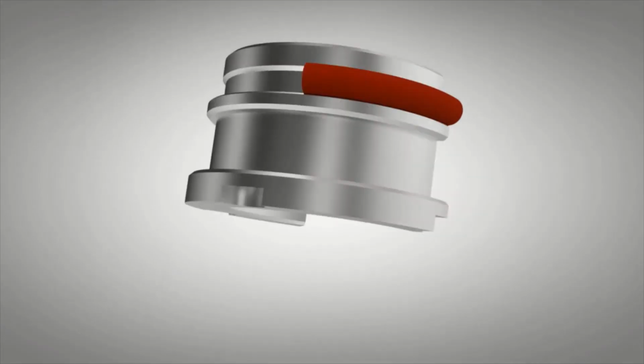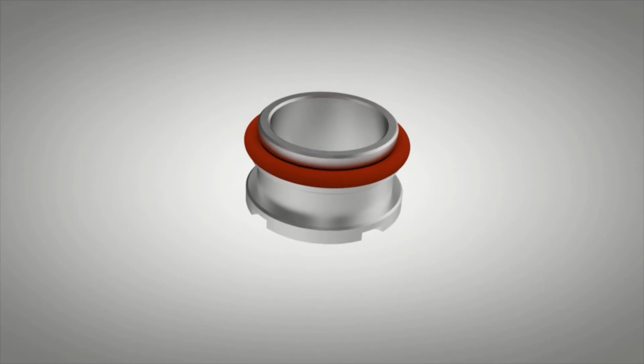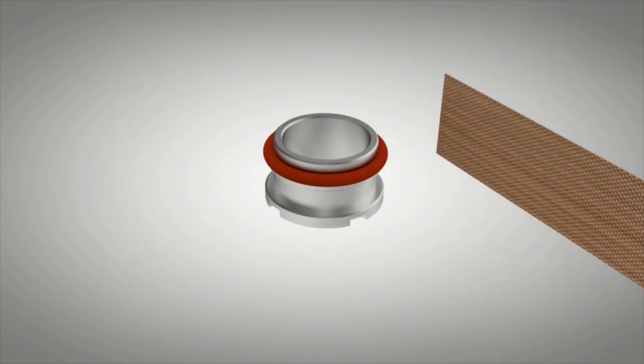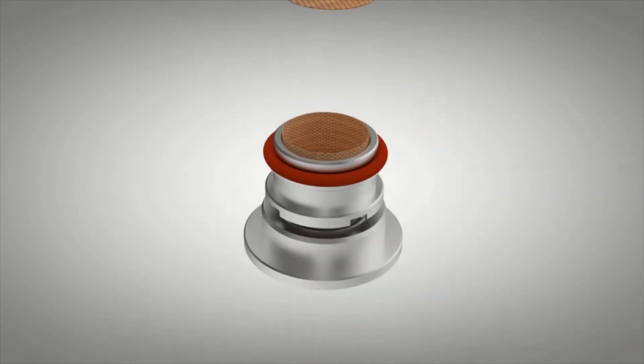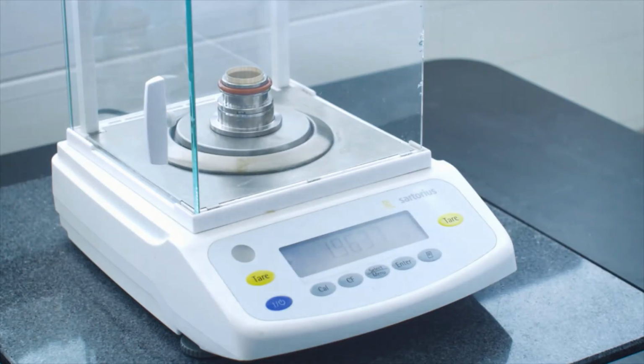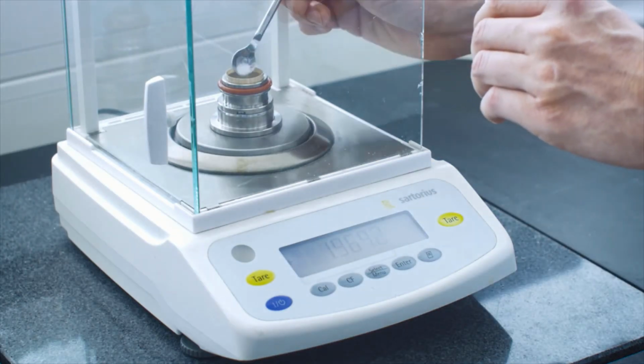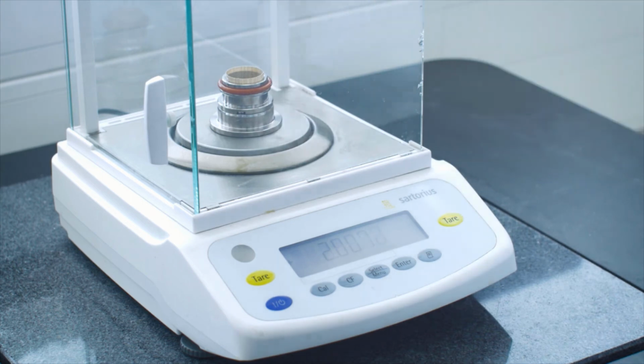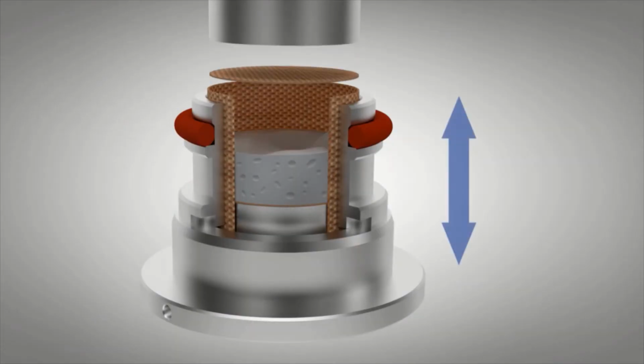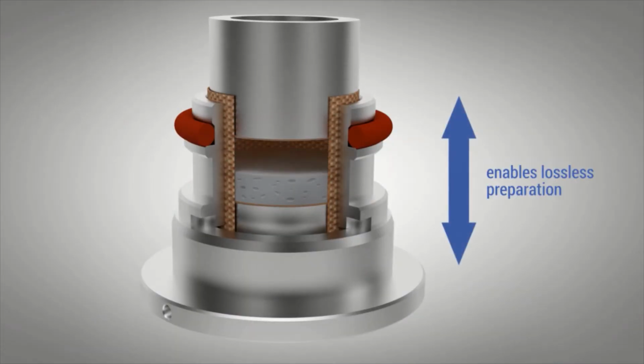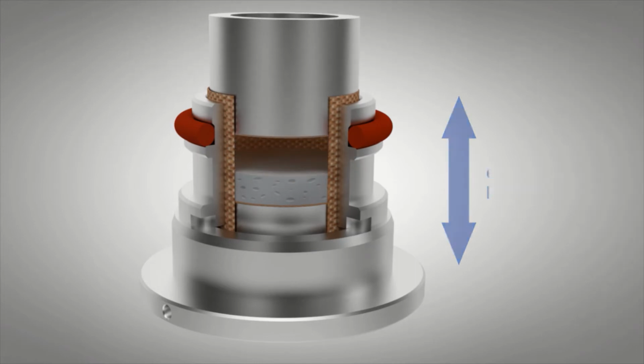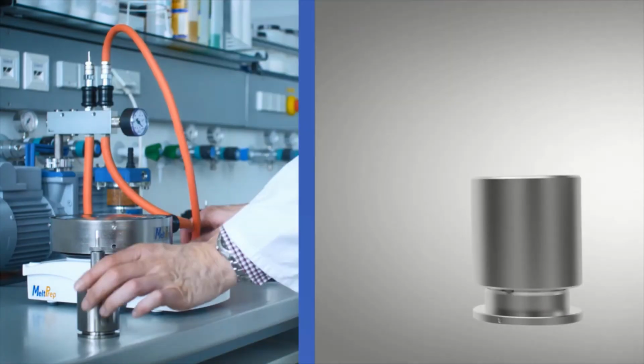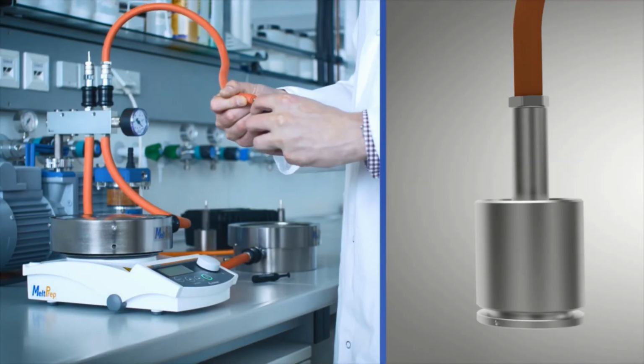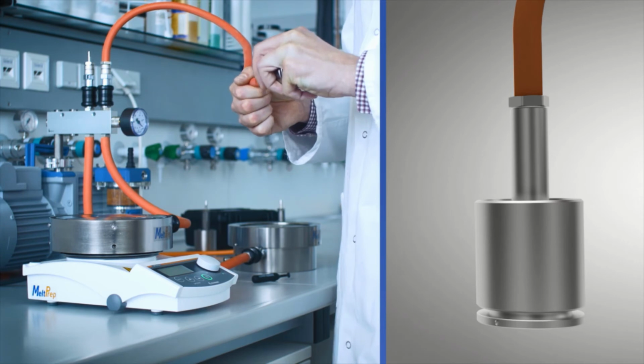This is the heart of the VCM technology. A PTFE foil is rolled up to cover the lateral surface of the VCM chamber. A disc-shaped foil covers the bottom. It is lightweight and can be filled on an analytical scale. After filling, the opening is covered with another disc-shaped foil on top. The foil arrangement allows the piston to go up and down. The volume of the chamber is adaptable and allows the chamber to follow the material behavior during processing.